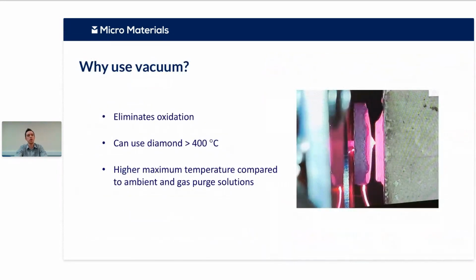So why do we need to use vacuum? This was again mentioned in the previous talk, but there are two key reasons. Firstly, to eliminate oxidation of the sample, and secondly, so that we can use diamond indenters above 400 degrees Celsius. Therefore, we can use this system to test at higher temperatures compared to an ambient system or even a system that employs gas purge to remove some of the oxygen from the environment.